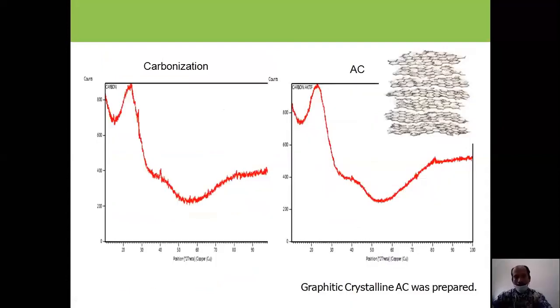We have already obtained activated carbon, and then we would like to see what happened with the structure. This is the XRD peak of our sample, the activated carbon, and for this you can see that it is already graphitic crystalline activated carbon was prepared. And if you compare with after carbonization, the peak in this one is much more smooth, so that we can say that some impurities are removed after activation with microwave.